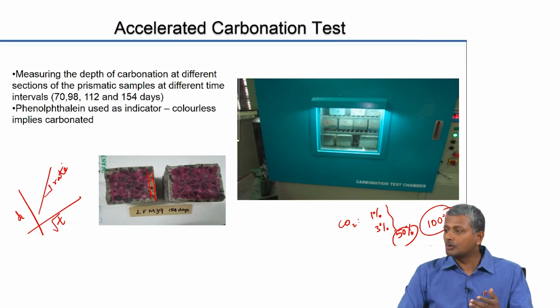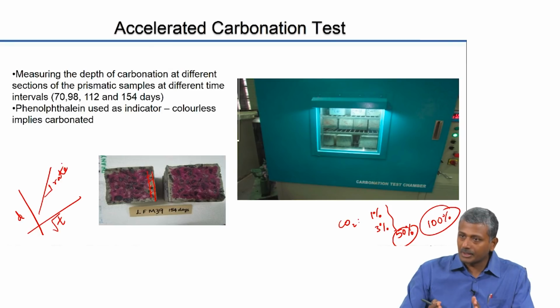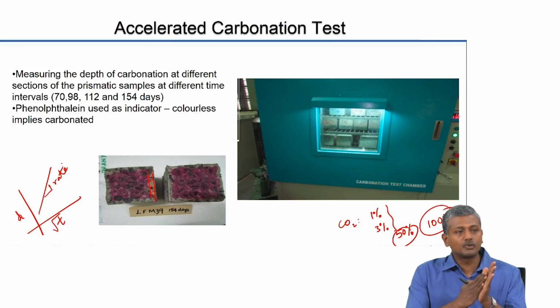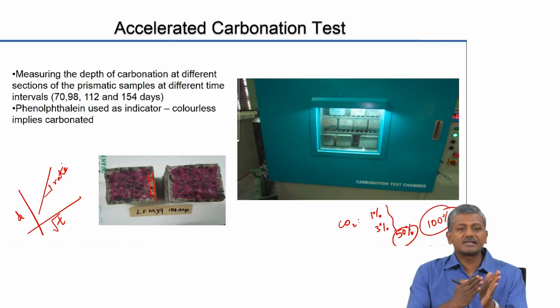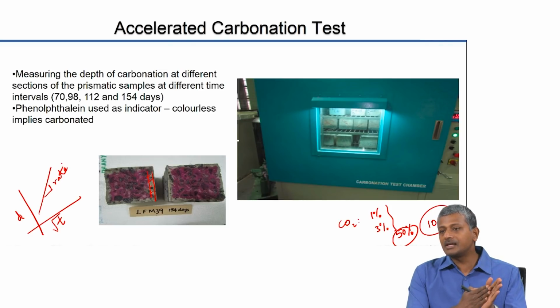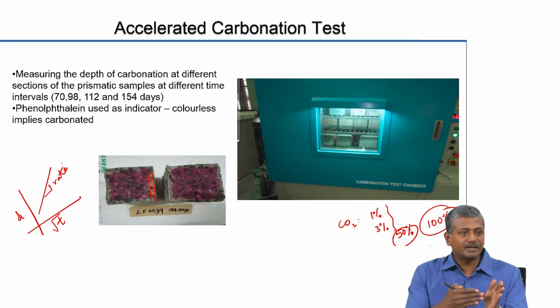Now, that would obviously mean that you consider that once the carbonation depth reaches the level of the reinforcing steel, because of the acidic conditions prevailing, the steel will start corroding at that point of time. It does not address the fact that when carbonation happens, the moisture content is rather low in the system, and the steel would need moisture to actually corrode. So, there is a dichotomy here.